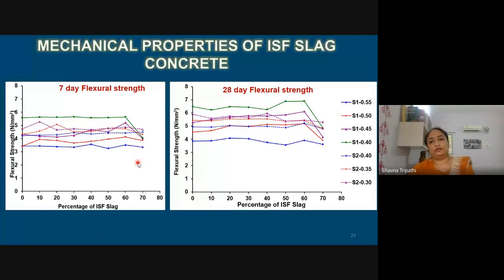We had also examined the flexural strength. In flexural strength specimens, this was very clear that up to 60% only we are getting strength which is comparable to control specimen. And all of the specimens having 70% ISF slag were having a significant decrease in flexural strength. The reason could be clearly attributed to lack of paste in 70% samples.